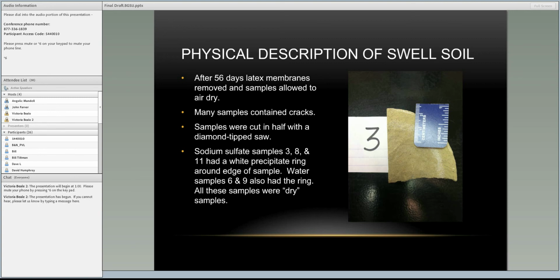So what we feel might have happened with this sample is that there was more primary ettringite formation, which then slowed down secondary ettringite formation. But additional testing would be needed to confirm that that's what happened. Therefore, considering things like mellow time and the amount of water and the amount of sulfate put into the soil initially is important. As for acknowledgments, we'd like to thank Jeff Wigdahl at ODOT for all of his help.